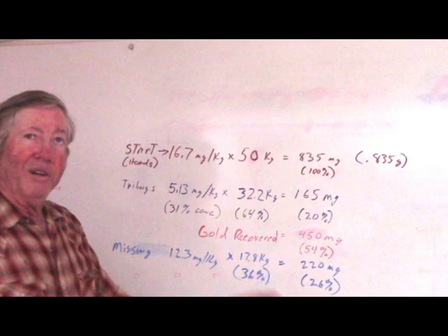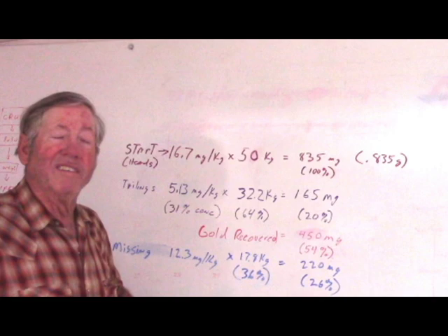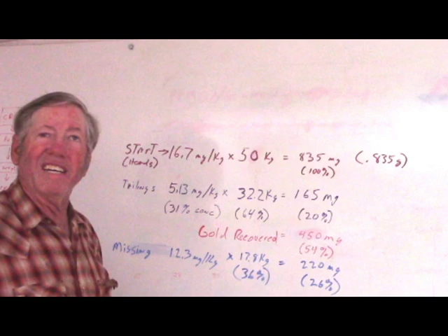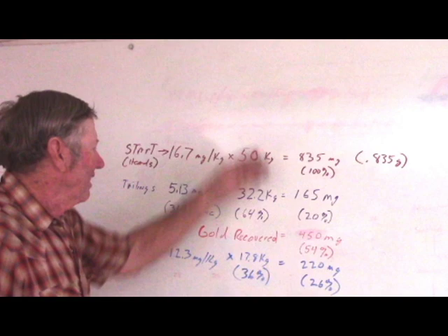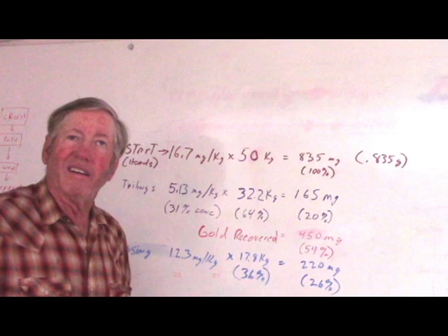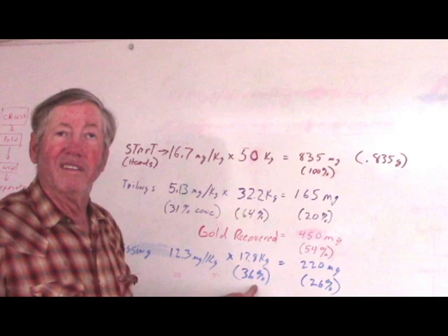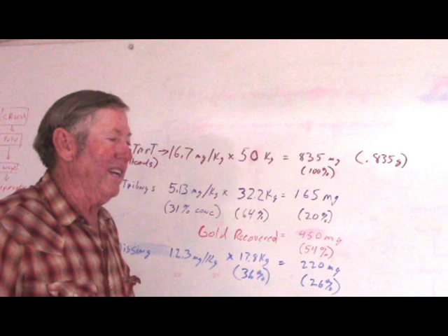I'll have to clean the whole table, the whole thing. When I'm done, I'll just have to take the time, it's going to be a day or so to let it all settle, then slowly, carefully drain it, let it dry a day or so, scrape it out of the catch tub, dry it, weigh it, and assay it. Then I can see where the gold is going. If it's in the slimes and it's still free gold, there's a couple of possibilities there in terms of how to deal with it. Number one, just go ahead and rerun it. I mean this is 36% of what you started with. Rerunning that doesn't take nearly as long. You can run it at lower flow rates, just essentially run it more gently.